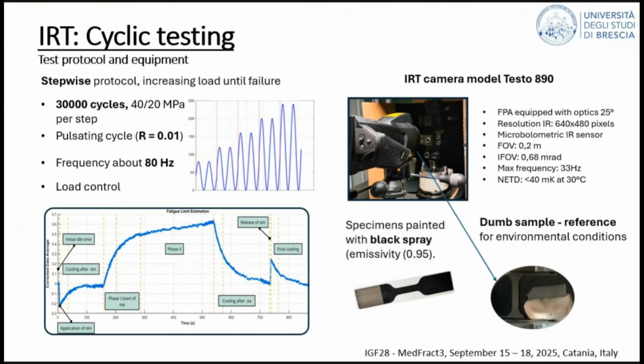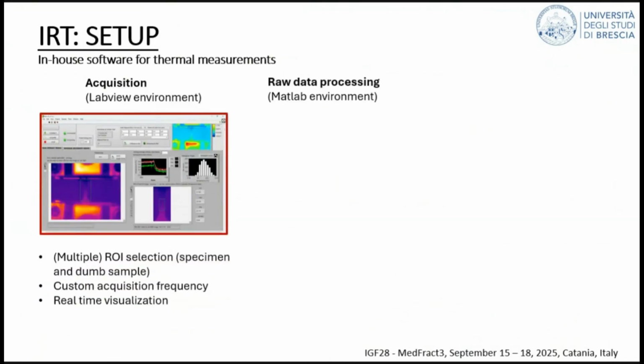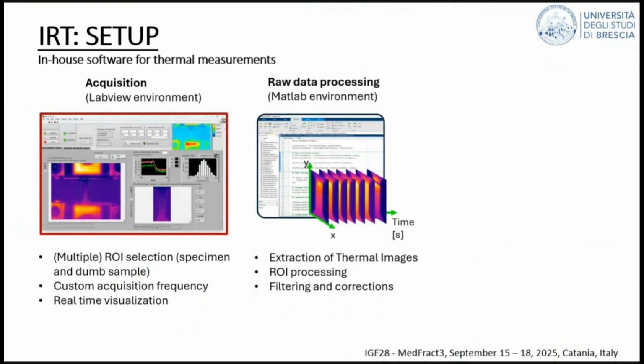We have a standard infrared camera with a microbolometric sensor, and we spray the sample with paint having a known emissivity, and we place a dummy sample close to the test one to have a reference for potential environmental changes. Then we had to set up some scripts in the LabVIEW and MATLAB environment for the acquisition of the thermal images and customization of some aspects of processing.